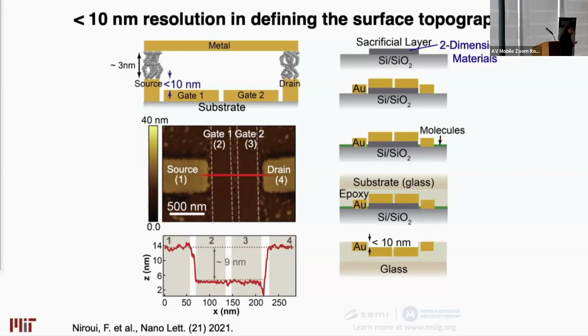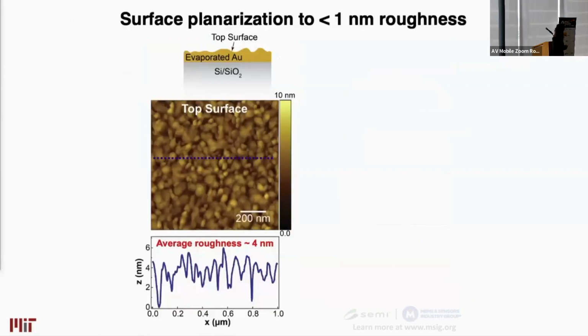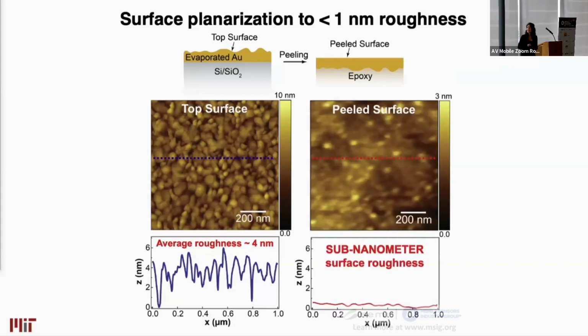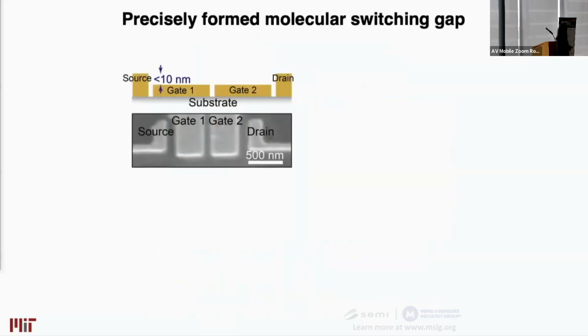So an additional advantage of this technique is that it actually allows us to also achieve planarization of the surfaces. So here I'm showing you an AFM of a deposited gold film, which gives you on the order of a few nanometer roughness. Through the planarization technique that we have, the same film can be made sub-nanometer smooth, which you can imagine can be very critical when you're trying to make devices that are on the order of the roughness that you have. So you go ahead and fabricate the bottom electrodes.